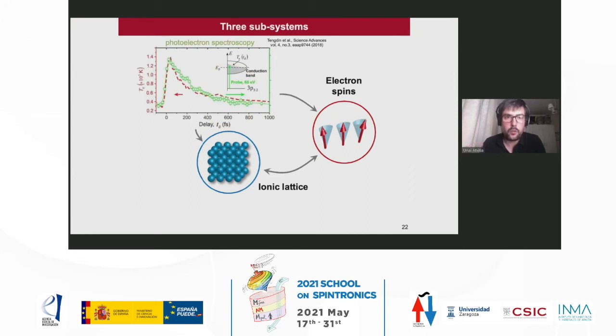One can use photoelectron spectroscopy to measure the electron temperature dynamics. So what these experiments can do is look at the distribution of the electrons around the Fermi energy, and from there they can fit the distribution to a Fermi-Dirac distribution and obtain the effective electron temperature.